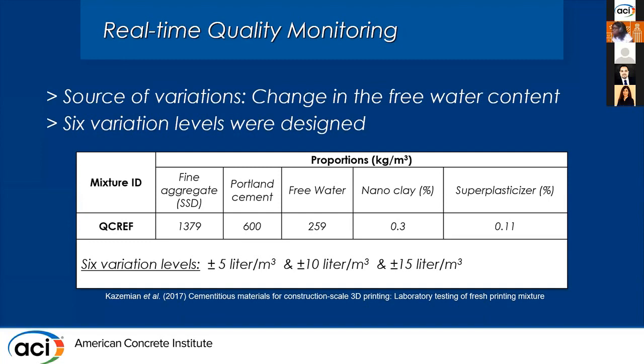I have a reference mixture, I called it QC-ref, and that was basically from a previous study that I did in 2017 with respect to performance-based testing of fresh concrete in construction 3D printing. And then I intentionally changed the amount of free water in this mixture by plus minus 5, 10, and 15 liters of water per cubic meter of concrete.